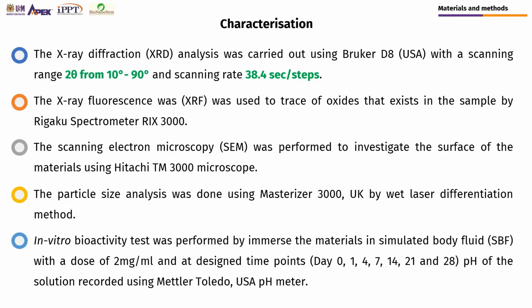The in vitro bioactivity test was performed by immersing the materials in simulated body fluid with a dose of 2 mg per ml. The pH was recorded at designated time points.